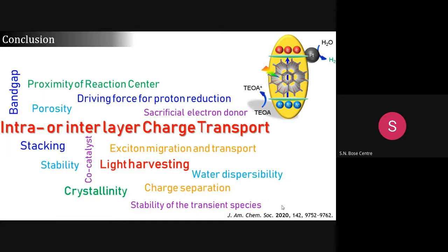If you increase the stacking also, you may not get a very high increase in performance, unless the stacking is affecting the charge transport. But if you increase the charge transport from 1 to 2, you may get the hydrogen evolution almost 10 times. So this kind of observation we got from this result. All these combined parameters are important, but charge transport plays one of the important roles in this kind of catalysis.